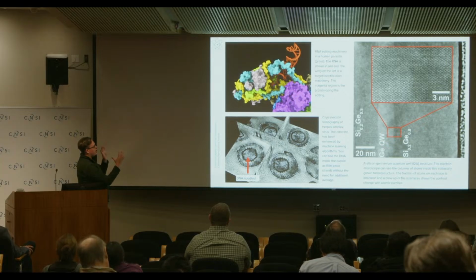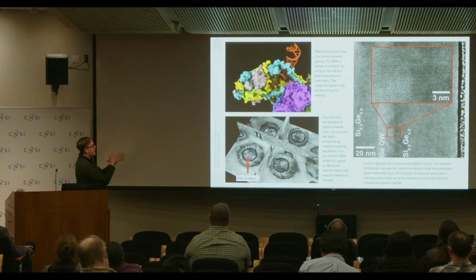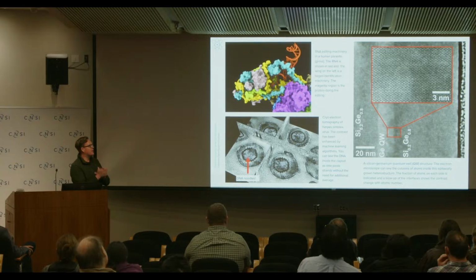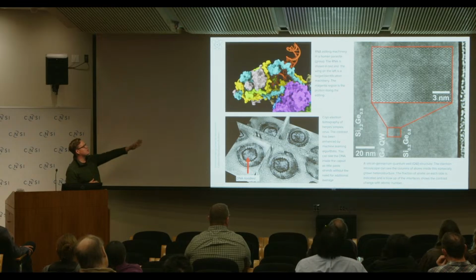When we do tomography, we can actually see inside of these objects in 3 dimensions. These objects can't really form crystals that well, so this is the only technique to look at this at really high resolution. And in the capsid we showed earlier, we'd removed all the DNA, but you can actually see inside of this capsid here all these little noodles that are actually the DNA that's trapped inside of that little virus. Here's an example from the semiconductor side where you can actually see the structure inside of a quantum well.